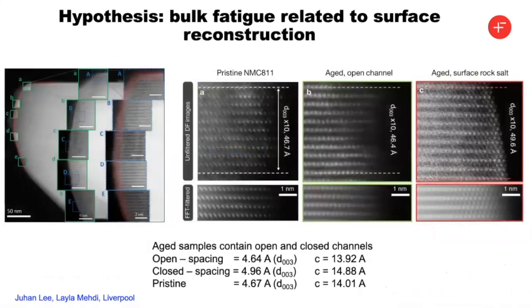And so what we found was extremely interesting when you analyze particles in more detail. These are materials that have been cycled for about 300 times, comparing a pristine one with an aged one, and you can still see open channels. And so this is material that's been charged to 4.2 volts, and then held at 4.2 volts, and then examined by TEM. And you can look at aged materials that have very similar spacings as the pristine material. So here's the pristine spacing, and here's the open channel in an aged material where they're very similar. But then when you have a rock salt structure, you see that there's a rock salt spacing which is larger, and that is seeming to pin the transition metal layers moving into the bulk of this material.